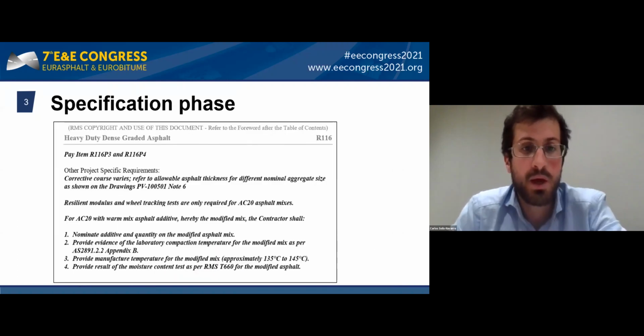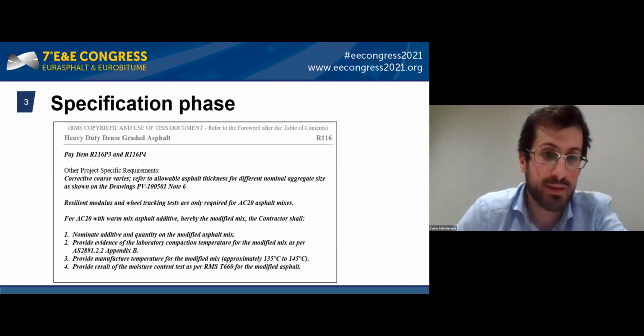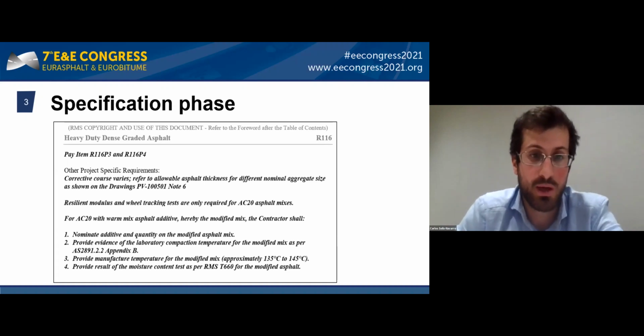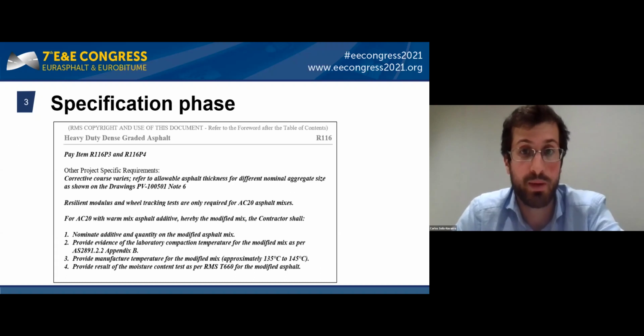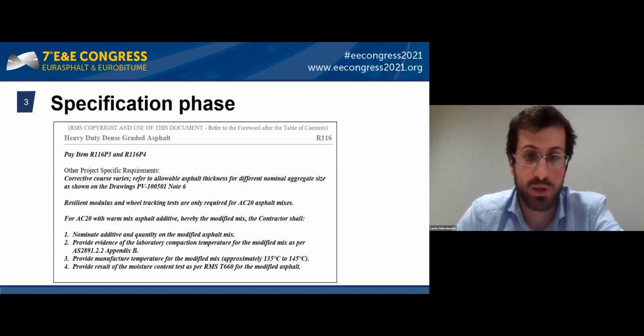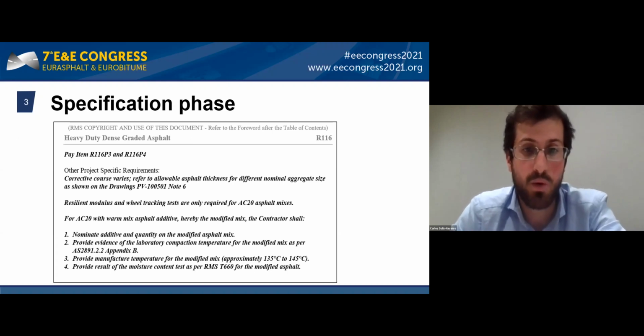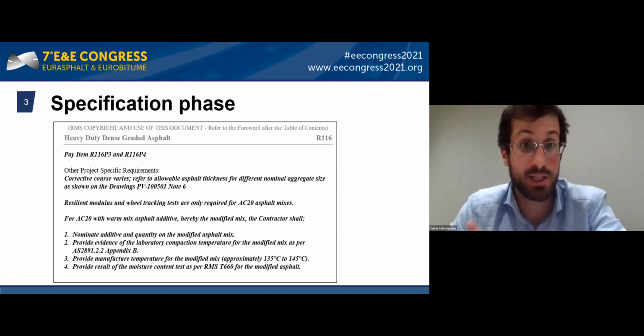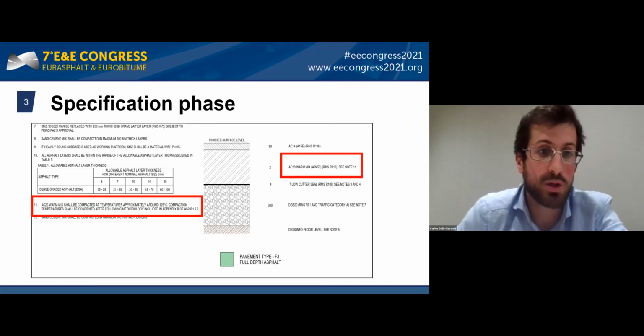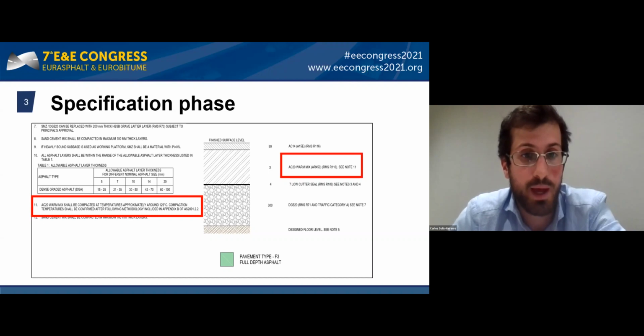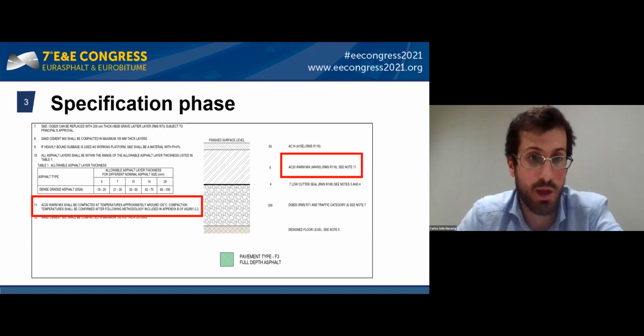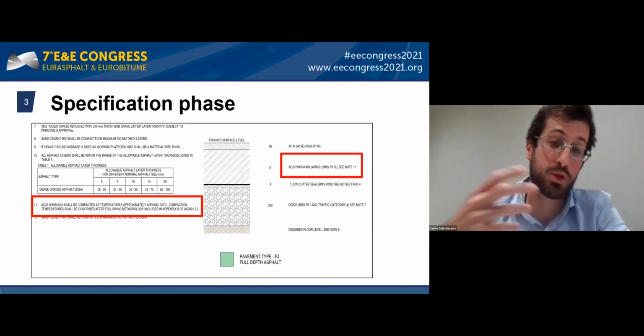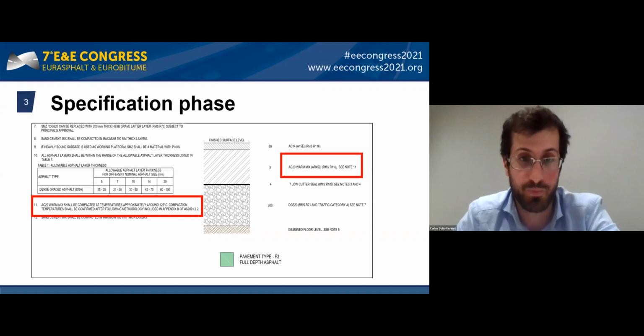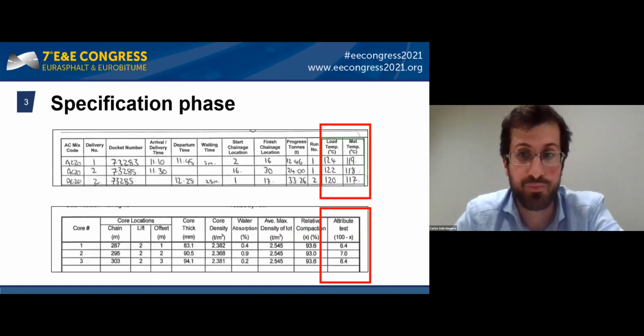Having this in mind, we decided that additional information was needed in our documentation, specification, and drawings. So we started to add all this required testing to the specification. Additionally, on the drawings, we added a note letting the contractor know that the temperatures have to be lower, and that they need to follow this methodology to calculate the warm mix temperature.